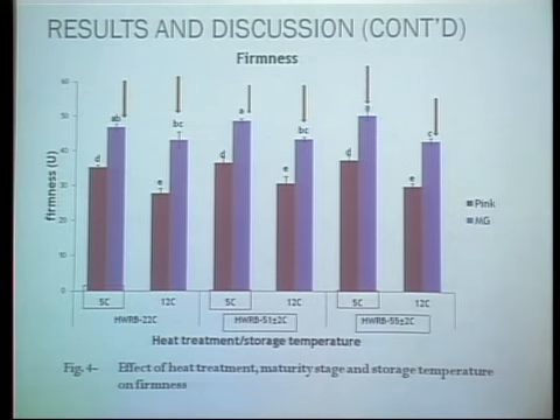And if we look carefully, when we did the student t-test, we noticed, even though there's no significant difference of the heat treatment, that these two treatments somehow were able to maintain the firmness of the fruit, that is at 51 and then at 55. But the recommended storage temperature, like I presented in my introduction, is 12. And as you can see at 12, the pink was not the same, but in 51 and 55, it was much higher. And we think that this heat treatment was able to maintain the firmness.